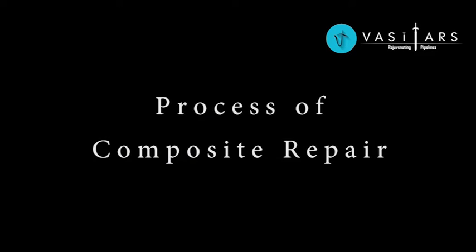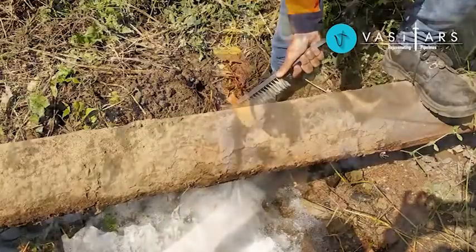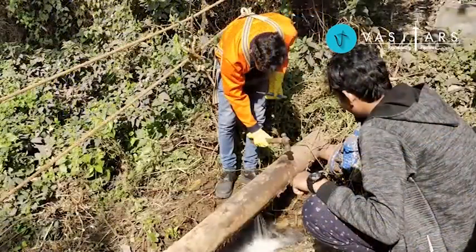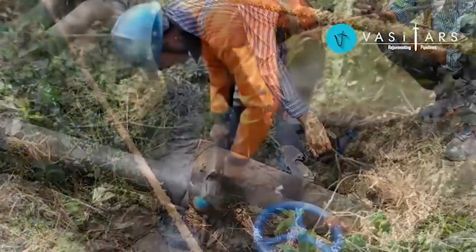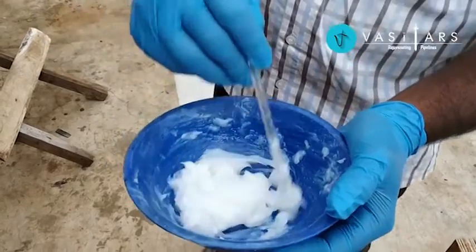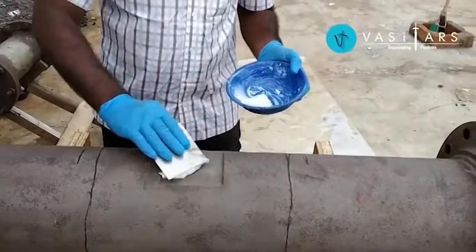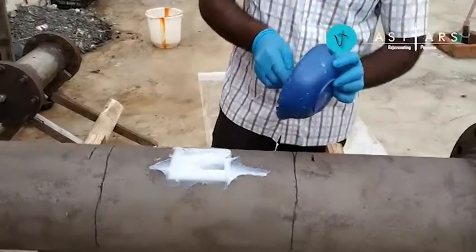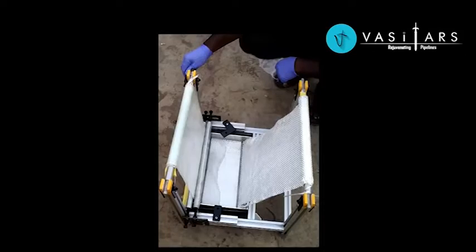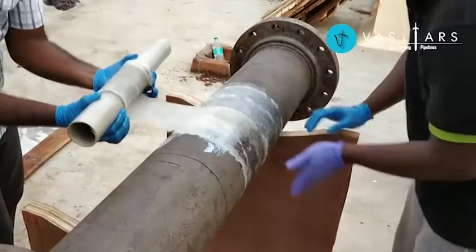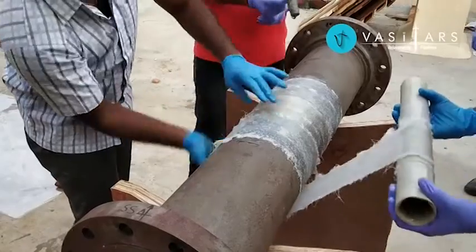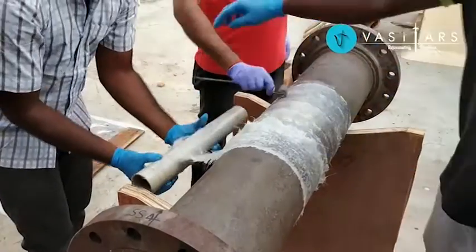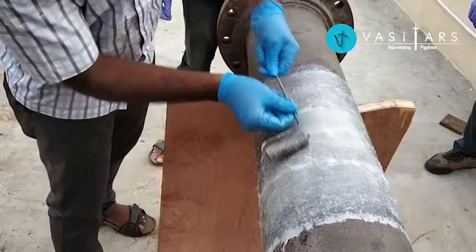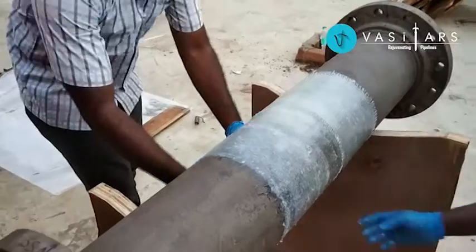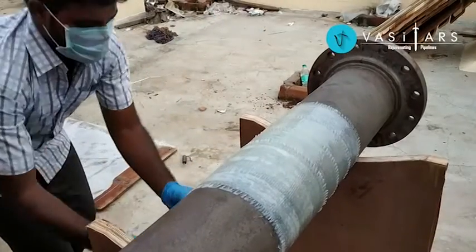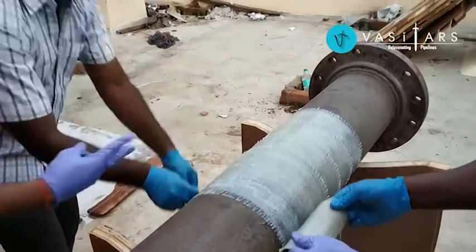The process of composite repair starts with the surface preparation of the substrate. Hand-operated tools are preferred in sensitive environments in the context of safety. Local wall loss defects are filled using the in-house developed interface adhesive paste. Fibers for wrapping are pre-wet using the fiber wetting mechanism. The fibers are wrapped around the defect region by trained executives with uniform tension and continuous rolling to ensure proper distribution of resin and a defect-free repair. The repair sleeve is let to cure for 12 hours to regain the original strength of the pipeline.